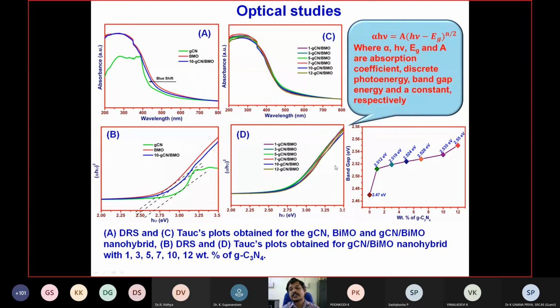Then later we studied the optical property of this material. It shows visible light absorption capability. Then we measured the band gap. The addition of different weight percentages of graphitic carbon nitride leads to an increase in the band gap value. So that is more beneficial for us.